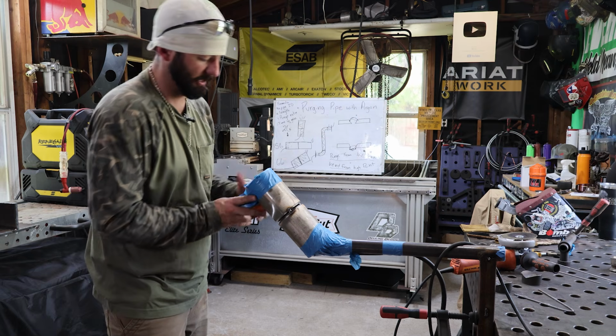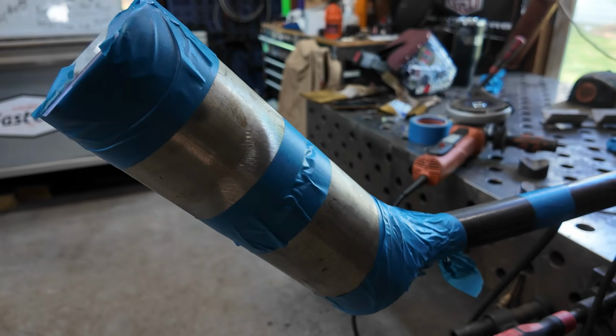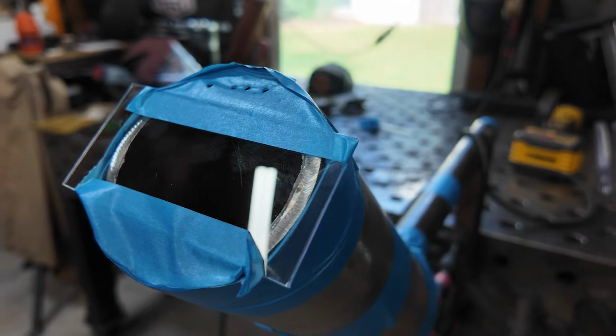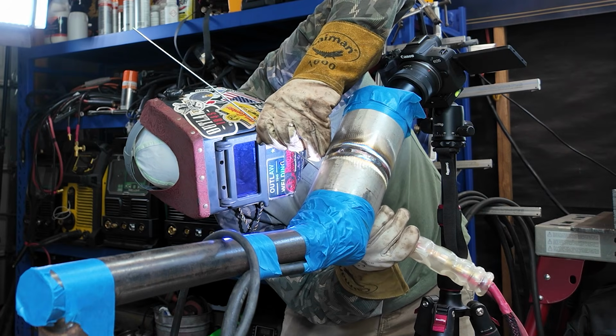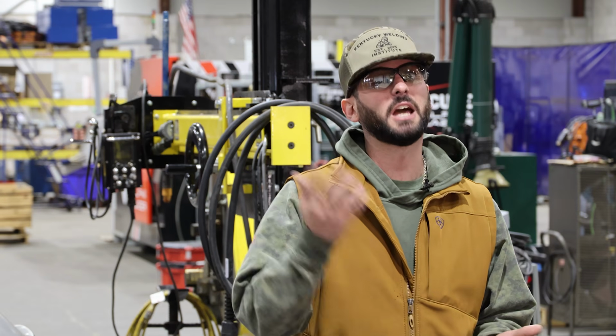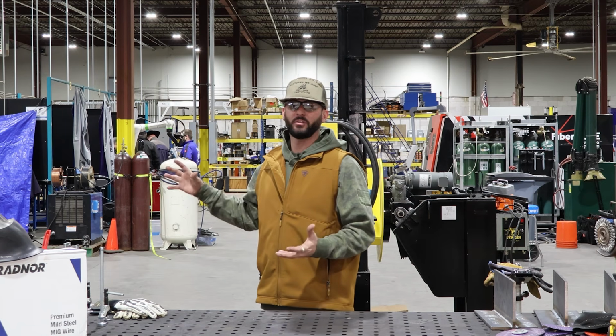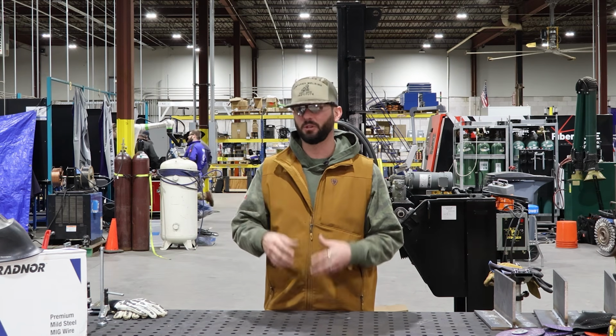So it's really good for pushing atmospheric air out of piping or whatever it may be in order to purge it so that you can put a good weld in, and the inside of it is also not contaminated with any atmospheric garbage or gobbledygook like porosity. Typically, you only have to worry about this when you're welding metals that have a little bit of chrome in them or a lot of chrome in them. And it's also just a great base for these other gases to come in on top of and mix up.